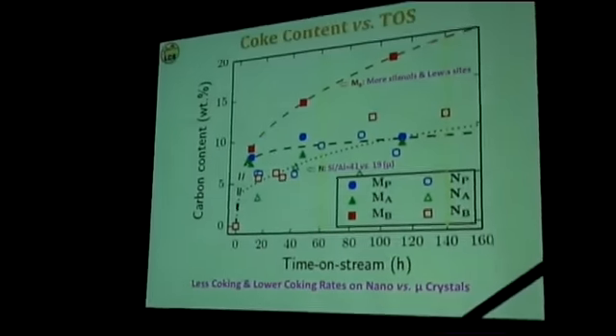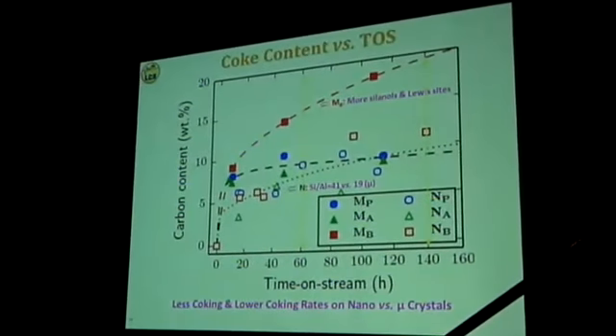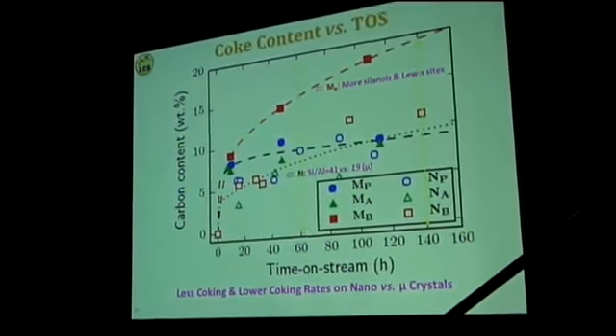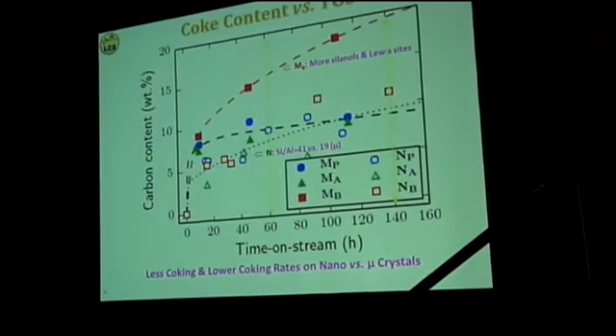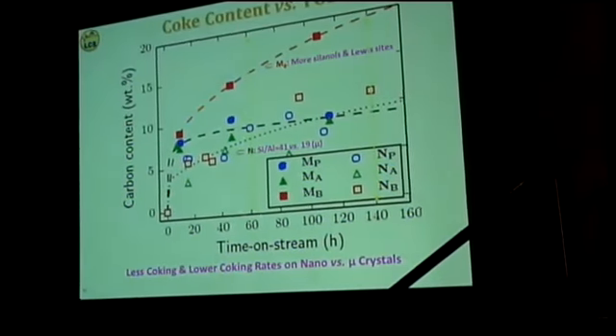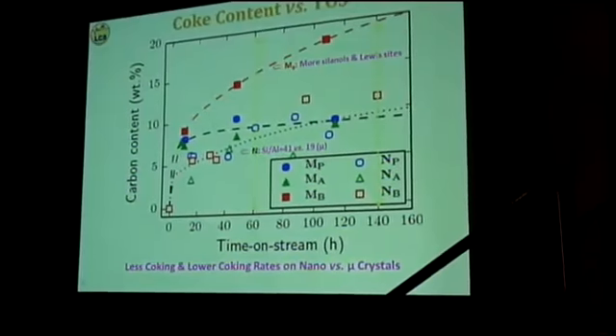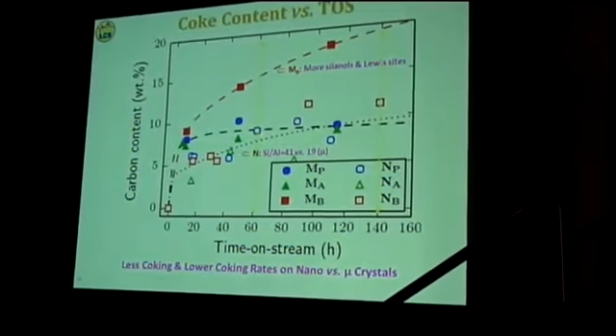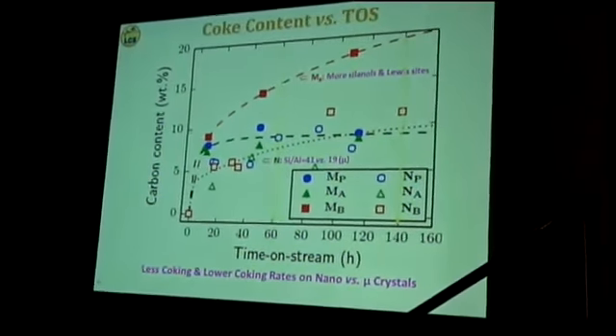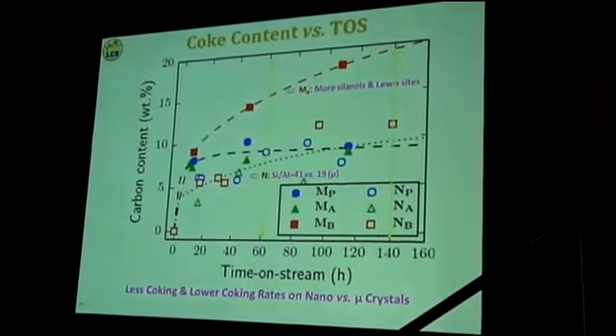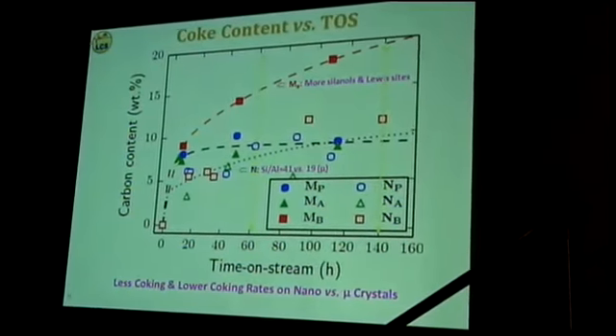If we look at these materials, it would be interesting to have a look at the molecular description of the coke at two levels in order to describe the materials after 60 hours on stream. We will compare basically the same level of coke on all catalysts with the exception of this one, and so we also try to have a look, especially for this material, at 140 hours.